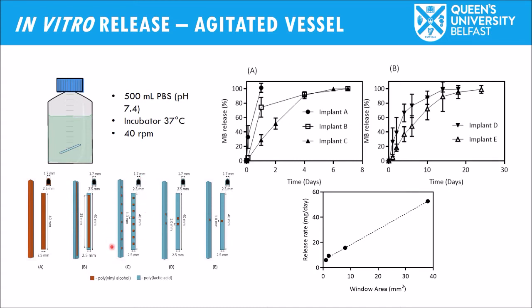Subsequently, we have implants with little soluble windows, but spaced evenly. That implant will provide a more sustained drug delivery, but still we will get only up to 1 week of drug release. Whenever we start to reduce the number of these windows, we can see that these implants are capable of providing a more sustained drug delivery. And actually there is a clear correlation between the drug release in milligrams per day and the window size.